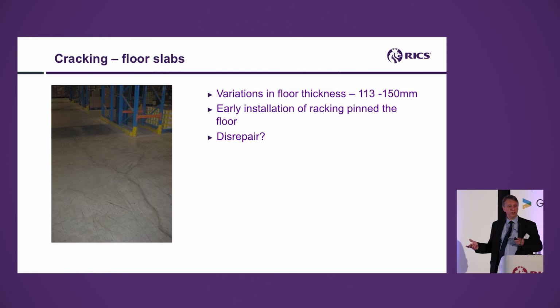But we went a bit beyond that, and we found that the slab, whereas it had been designed at 135 millimetres thick, steel fibre, was actually only 113 in places. And logic says to you, well, if we needed 135 and we've got 113, it's not going to be strong enough. And we ought to be restricting the amount of load that's put on those racks.